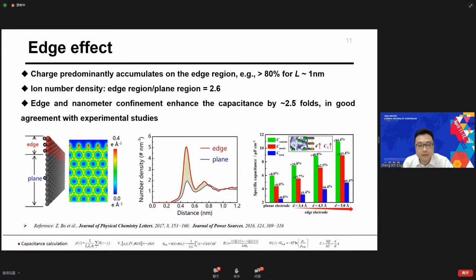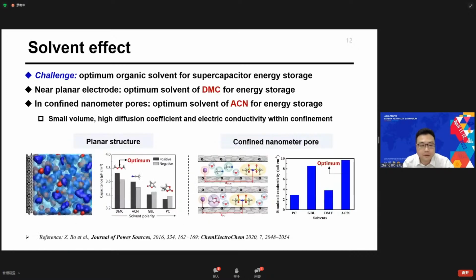Here we propose a combination of DFT and MD. We use DFT calculation to obtain the charge distribution for the electrons, and we use MD simulation for the ion distribution. The results show that the edges and the nanometer confinement near multi-layer graphenes both contribute to the energy storage increase, leading to a 2.5-fold capacitance enhancement.